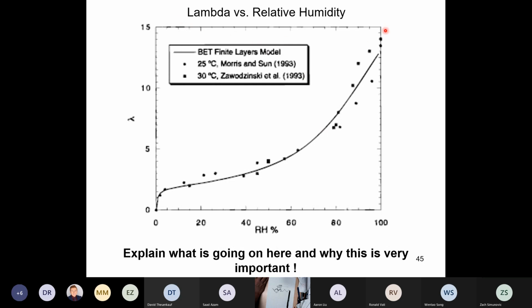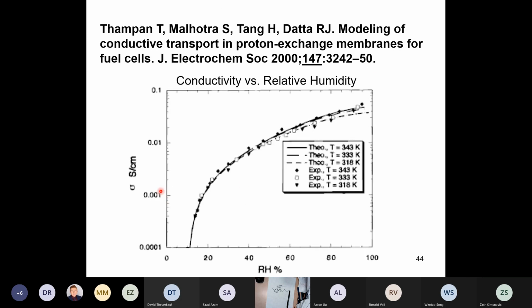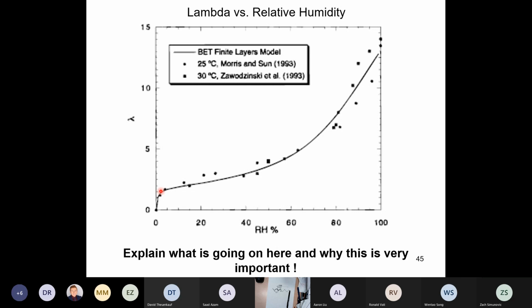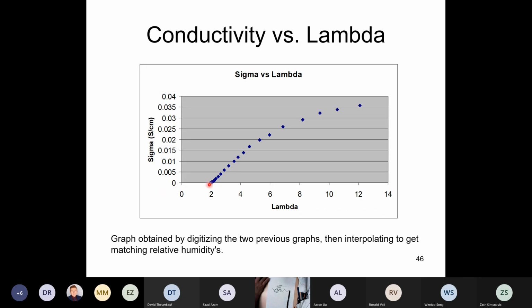And then here's another plot that shows lambda, which is the water to sulfonate ratio, plotted versus relative humidity. So you can see how the water to sulfonate ratio depends on the relative humidity. And then you can take this graph and plot what you really want, which is how the conductivity varies with lambda. And now you can see that when lambda is small, you're in deep trouble, and the conductivity kind of saturates at larger values of lambda.